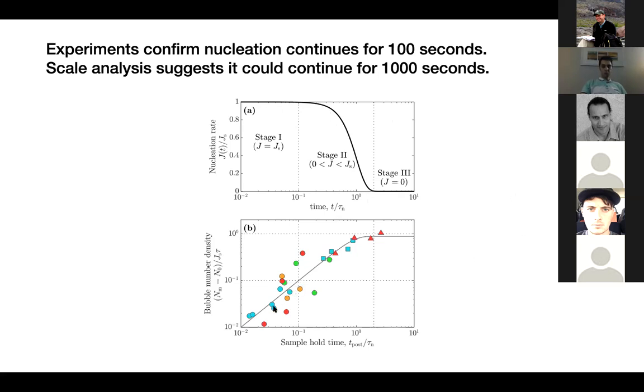Our experiments mostly fall in the first stage, several of them in the second, and only one of them was at the equilibrium stage. The time scales of these experiments are about 100 seconds, indicating nucleation continued for 100 seconds. The nucleation time scales that we inferred from these experiments are on the order of 1,000 seconds, suggesting nucleation could continue for 1,000 seconds. Now that our experiments verify that nucleation can be continuous, let's look at under what conditions in eruptions it can be continuous.